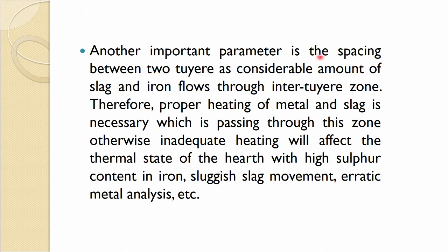So, another important parameter is the spacing between two tuyeres, as a considerable amount of slag and iron flows through the intertuyere zone. You will understand this in the next slide. Therefore, proper heating of metal and slag is necessary which is passing through this zone. Otherwise, inadequate heating will affect the thermal state of the hearth with high sulfur content in iron, sluggish slag movement, erratic metal analysis, etc.